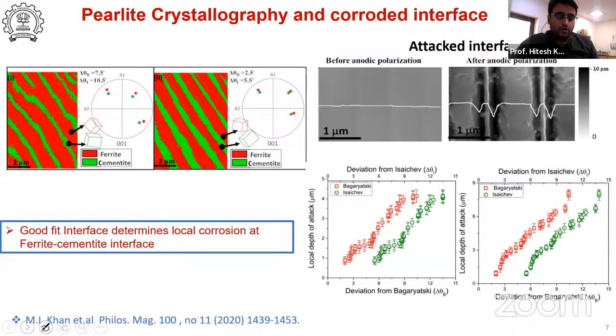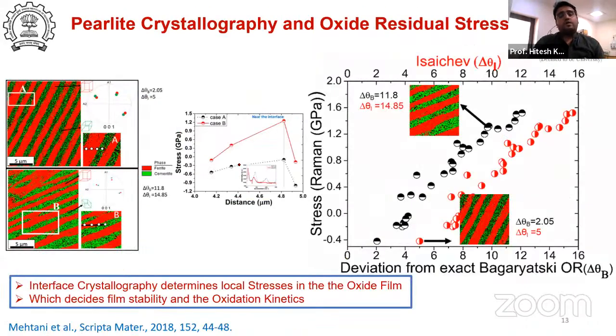Then we also calculated the stresses. These stresses are calculated with the help of Raman. These are Raman hydrostatic stresses. In this, the same way, we marked each colony and oxidized it in a controlled environment. Controlled environment means 99% nitrogen and 1% oxygen was given, so that the oxide layer forming on the material surface should be thin, so that we can identify each colony. And then we calculated the Raman stresses on the particular colonies.